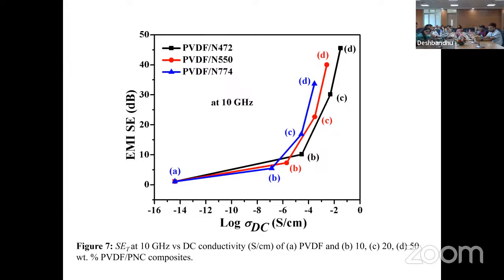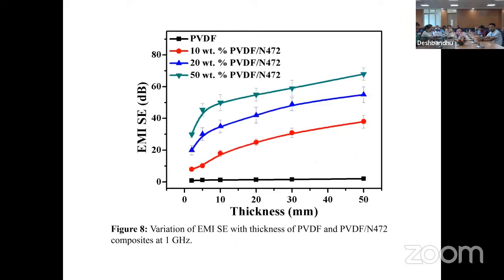I have shown the effect of electrical conductivity on the EMI shielding, because you can see as the electrical conductivity increases, the EMI shielding also increases. So the EMI shielding is directly proportional to the electrical conductivity of the material. This is also the EMI shielding effect on thickness. As you increase the thickness of the material, EMI shielding is going to be higher and higher.